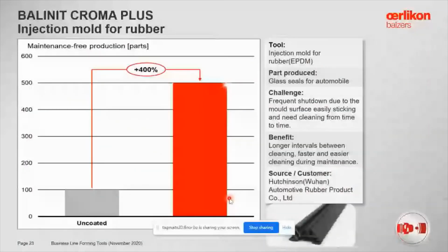Another example for an injection mold for rubber. Of course, this is a different rubber, EPDM, for glass seals for automotive. And here we can see the frequent shutdowns. The challenge was frequent shutdowns for mold surface, easy sticking. But after coating with BALINIT Chroma Plus, we could improve the tool life by almost a factor of 5 times more life. This is also a customer from China in Wuhan, Hutchison Automotive for rubber products.